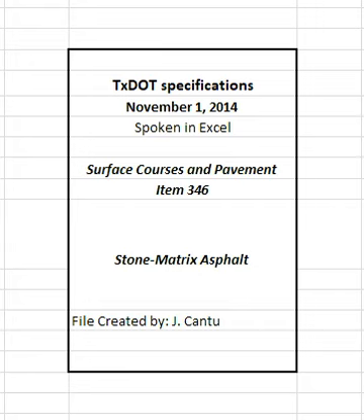If the optimum asphalt binder content for JMF2 is more than 0.5% lower than the optimum asphalt binder content for JMF1, the engineer may perform TEX 248F on Lot 1 to confirm the mixture meets the overlay test requirement of 200 cycles.